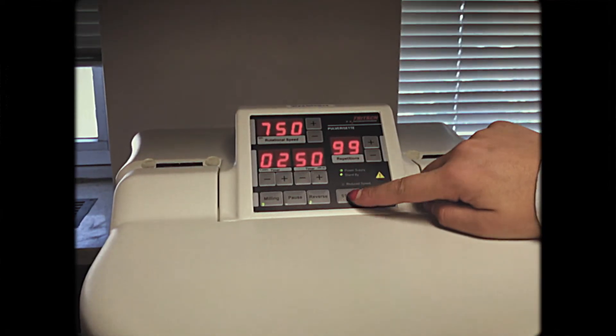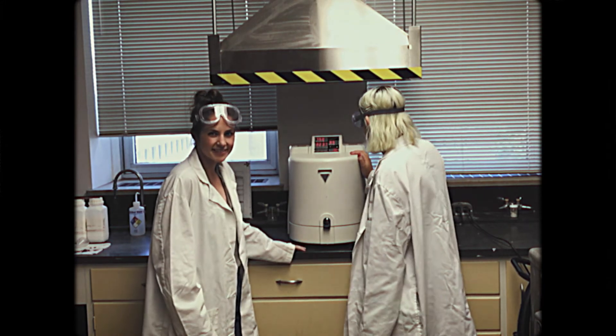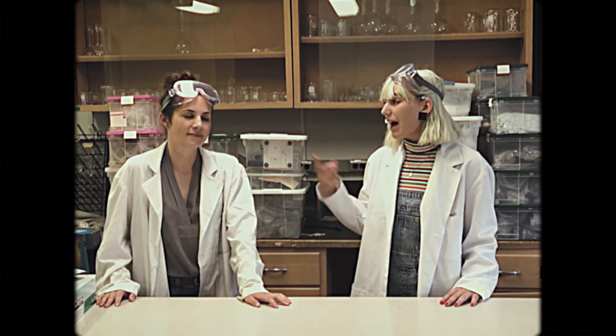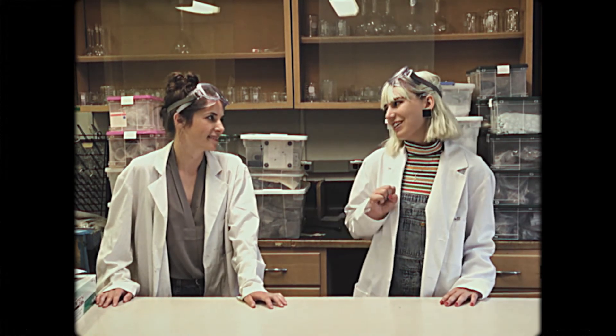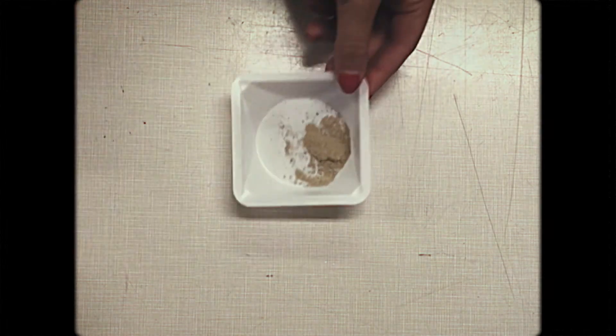Then we just push a button and voilà. It's that easy? Yes, because science is that easy. The pulverizer spins at 750 rotations per minute — very fast. As it's spinning that fast, the balls mill the powder into the fine grain size we need. We take the slurry we made from the milling process and dehydrate it so that it's super fine-grained powder.